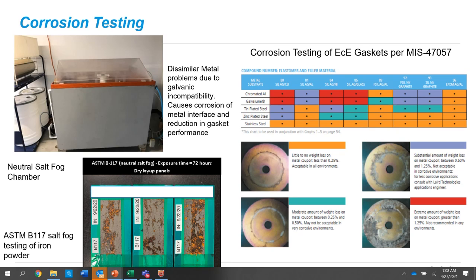It doesn't corrode. But the other problem you have is you've got the metal corroding, but then the other problem is the filler inside can corrode as well. And when that happens, the way these conductive elastomers work is that they have what's called a percolation threshold. So you've got all these conductive particles touching, and that's what gives you the electrical path through the rubber material. As you start corroding those particles, you lose that connection and you start degrading the performance. So you've got to worry about, one, corroding the metal that you're trying to protect, and then two is losing the performance. So that's all about selecting the right filler based on what your material is.